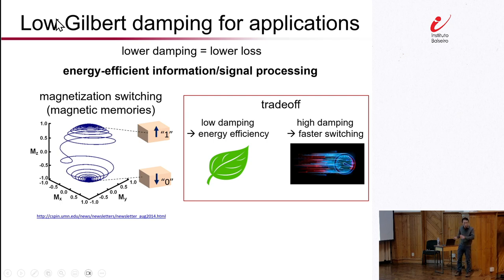However, there is a trade-off. By lowering damping, you actually end up slowing down the switching process. In other words, if you have high damping, you can get the magnetization to switch from one direction and converge towards the other direction within a much shorter time scale. So this is a decision that you have to make if you are trying to make a digital memory device. Do you want better energy efficiency or faster speed? There is a trade-off.